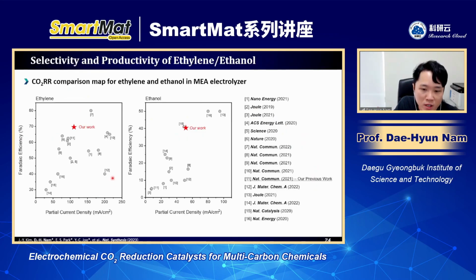So if we compare the performance of the ethylene and ethanol in terms of the Faradaic efficiency and the partial current density, although these are not record ones, the most interesting point is that this is the first work to convert a very highly selective ethylene catalyst into a highly selective ethanol one. So in this way, we could find how we can control the selectivity between ethylene and ethanol.